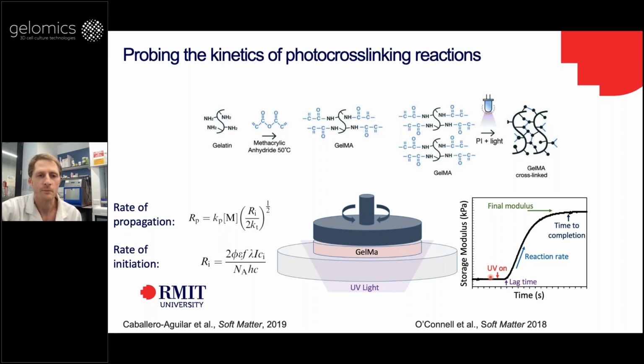So, for example, here's the evolution of a typical photocross-linking reaction, where you turn on the UV light, and you can monitor when that reaction starts to occur, and then when it reaches a plateau as it's reaching completion. And already from the shape of the curve, you can learn a lot about what's going on during the reaction. You can learn about the oxygen inhibition by the lag time, so how long it takes before you start to see an increase in stiffness.